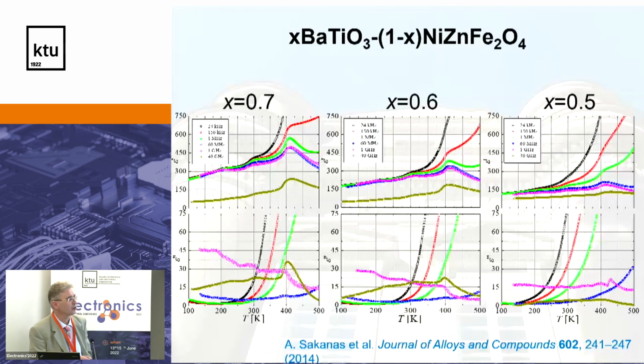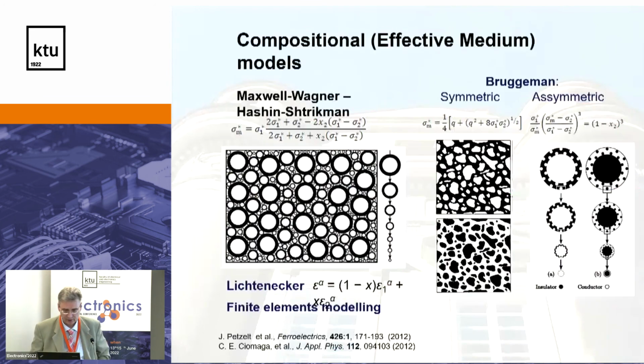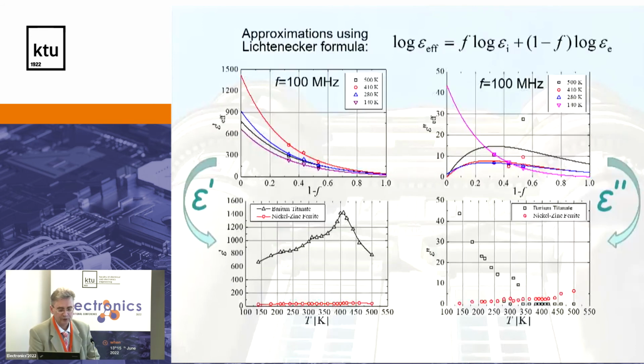The same is barium titanate with nickel zinc ferrite, which I skip. But an interesting thing is that you need to extract the separate contributions, because you have a composite. You have barium titanate and you have cobalt ferrite or another magnetic material. So there are different theoretical models. One of them is Maxwell, Wagner, Hashin, Shtrikman, and Bruggeman, and Landau, Lifshitz, Looyenga. So we found that Landau-Lifshitz-Looyenga is the best model, and we used it to separate, and we succeeded, and we can see the contribution of barium titanate and the contribution of nickel zinc ferrite in the composite.